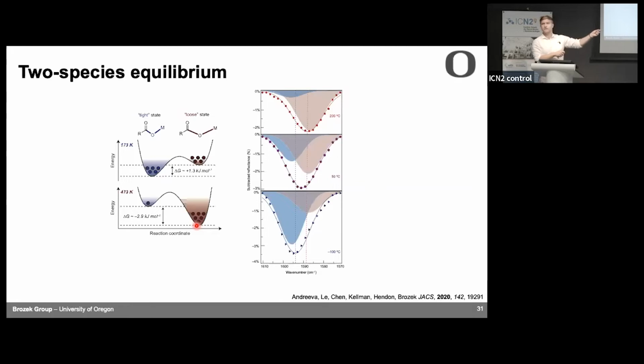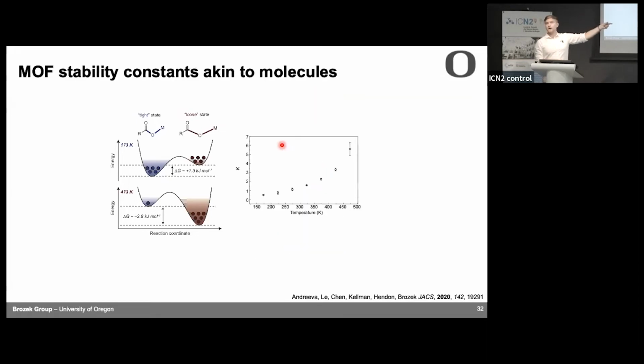And so if that's true, you should be able to see two species in your data. And so if you take the asymmetric stretch, they fit very, very nicely to two species. When we fit this, we didn't tell the program to fix where those two species are. It did that by itself. It decided that at low temperature, you mostly have a high frequency species. At high temperature, you mostly have a low frequency species. At intermediate temperatures, you have both. That's why the peak is broadest at intermediate temperatures. The other nice thing about this fit is that the area under those two curves, if you take the ratio of them, it gives you the equilibrium constant. So we can get all this just from fitting normal IR data.